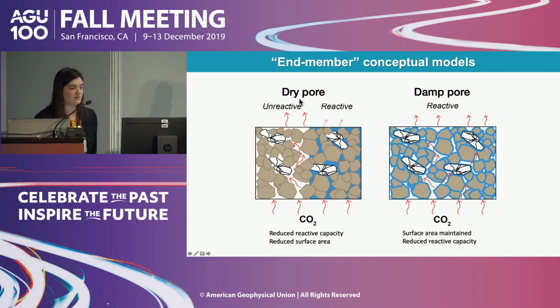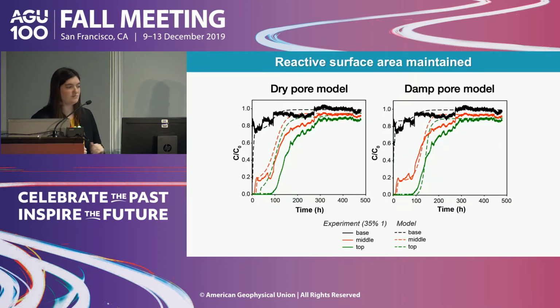In contrast, we have what we call the damp pore model, which assumes water is homogeneously distributed across all mineral surfaces. So the surface area is maintained, and therefore the reaction rate should be maintained, but still the amount of reaction possible is limited. And so we applied these models into Min3P with results shown here. The dry pore model on the left-hand side does a bad job of reproducing our experimental data. The damp pore model on the right-hand side does a better job of reproducing our experimental data.